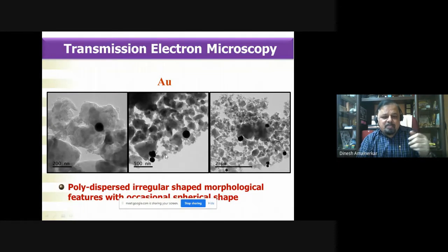Why do I say so? There is a reason for that. Here it is very clearly seen: there is a gold nanoparticle inside the amorphous insulating matrix of some inorganic material or combination of inorganic materials, which we don't know. So what we have seen here is polydispersity, irregular shaped particles. You can see particles from nanometer scale to micron scale, so a lot of polydispersity. Of course, there is no mechanization involved in that. Obviously, you cannot have control and cannot get a monodisperse distribution of nanosized materials in this kind of bhasma. This is the case of Swarnabhasma.